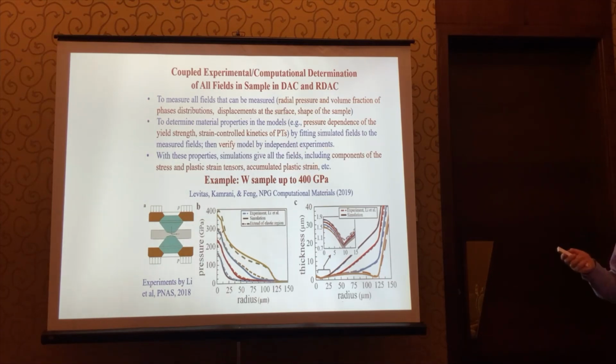So we need to understand something in this field. We need to know fields of stress tensor and plastic strain tensor. They are not measurable. So that is why we developed coupled experimental computational methods. And to prove concept, we took the most complex case, tungsten at 400 GPa. This is experiment from this paper.